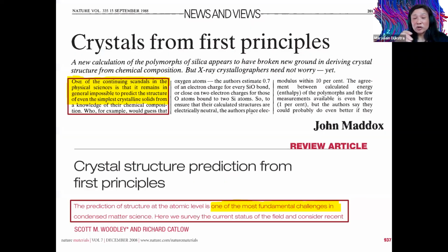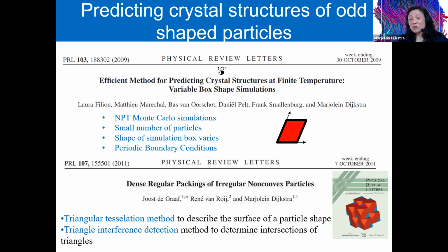And because this is a notoriously difficult question that was already raised by many people in the literature, we decided to work on this in the context of these colloidal particles. And we followed different routes, also genetic algorithms, evolutionary algorithms, but in the end we came up with an extremely simple method, which was just plain Monte Carlo simulations using a very small number of particles in the simulation box. So we basically simulated only the unit cell. The shape of the simulation box could vary, and we used periodic boundary conditions because we were interested in periodic crystal structures.